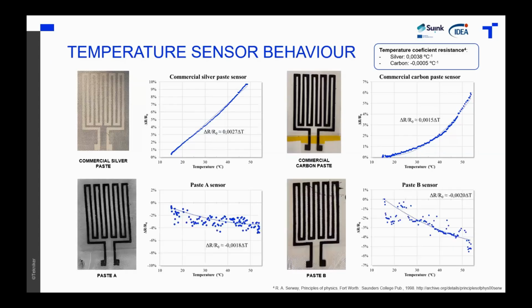And then we characterize the two that we made at Tekniker. It's true that our results are not as precise as the commercial ones, but it's a logical result in development. But we can see that both have a modification in their resistance when changing the temperature. We will try to reduce these imprecise points in next steps, but it's true that we can say that paste B behaves better than paste A for temperature